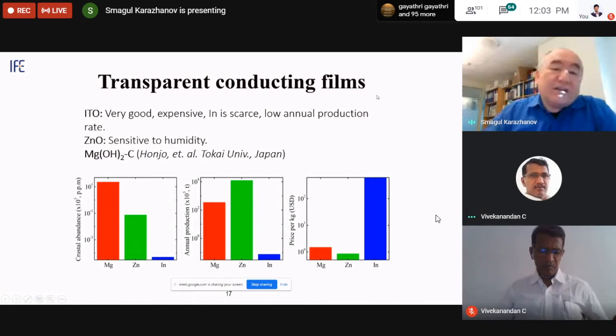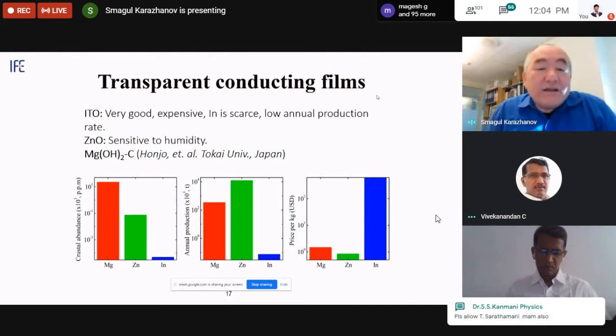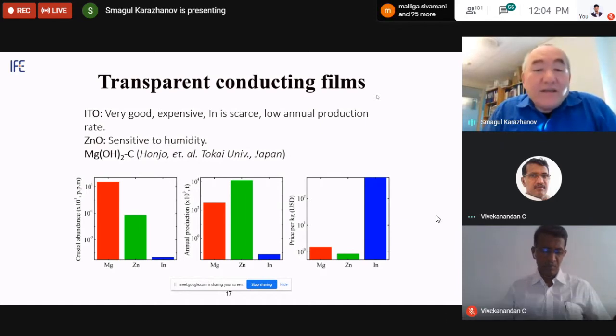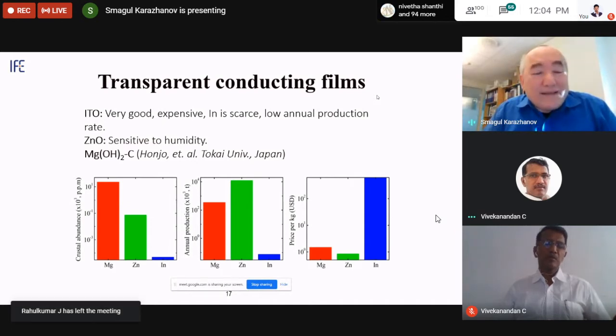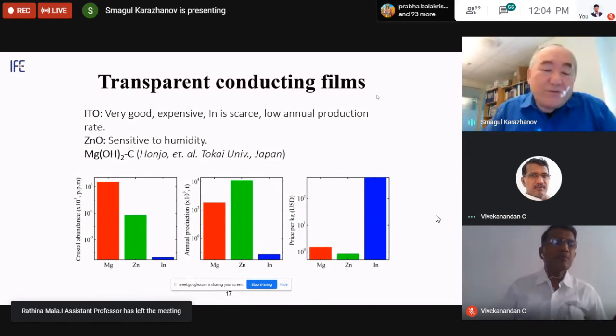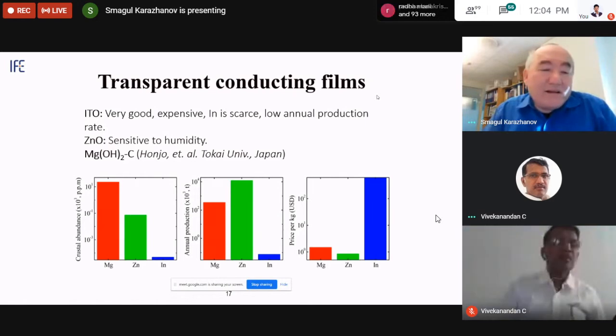The other challenges are in transparent conducting films. Not all silicon solar cells are using TCO layers, just some of them. The very popular one is ITO, indium tin oxide. It is very good, but expensive, and the scarcity of indium is a problem. Zinc oxide is okay, it is used in many types of solar cells. When it's in between two layers, it's okay, but when it's used as the outermost layer, it becomes sensitive to humidity when it's 200 nanometers or less. When it's above 200 nanometers, then sensitivity to humidity is not a problem, but then electrical conductivity and color become a problem.